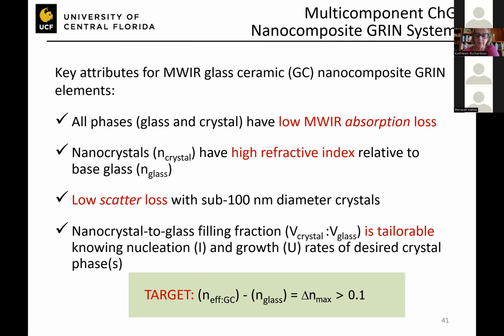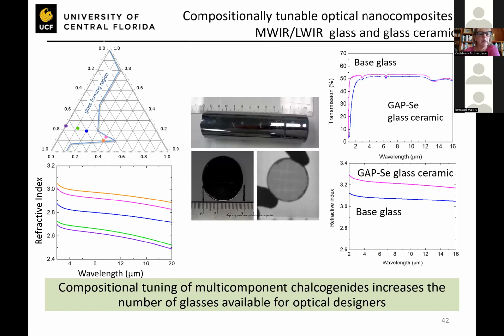There are very specific optical metrics that our glass ceramic must meet. And not only the optical properties, but the other physical properties will be a product or essentially an effective sum of the properties of the remaining glasses as well as the crystals that we have created. And they must be very small to make sure that we don't have scatter and loss in this composite. So we spent a lot of time working on this and have in both bulk and thin film form. It's shown here for a germanium arsenic lead selenide glass system, where lead is the key ingredient which promotes crystallization in a controlled way. But what you can see is that not only do we maintain transparency across the infrared in our base glass and our glass ceramic, but we have a huge change in refractive index that is available to us to engineer into an optical design platform.